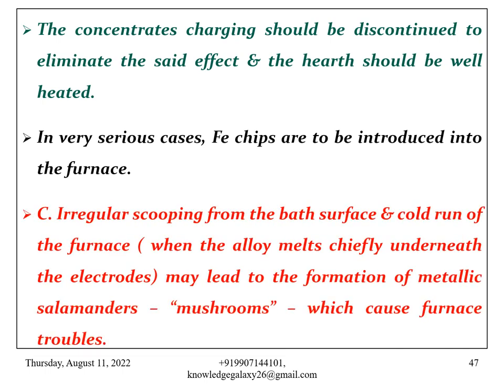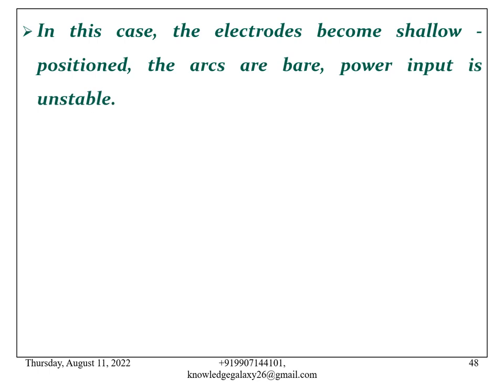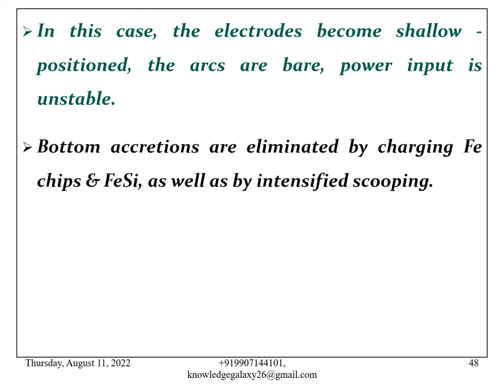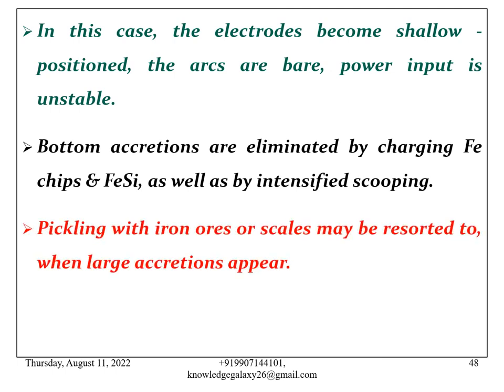Third abnormal condition is irregular scooping from the bath surface and cold run of the furnace. When the alloy melts chiefly underneath the electrodes, it may lead to the formation of metallic salamanders, which are normally called mushrooms, which cause furnace troubles. In this case, the electrodes become shallow positioned and arcs are bare, power input is unstable. Bottom accretions are eliminated by charging iron chips and ferrosilicon as well as by intensified scooping. This is the technique to overcome the above mentioned problem. Pickling with iron ores or scales may be resorted to when large accretions appear.